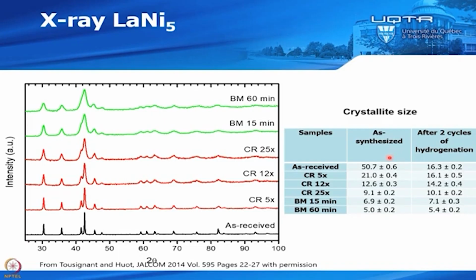So this is as received, it's 50, this is in nanometer, so 50 nanometer, and ball milling 15 minutes, you reduce that by a factor, almost a factor of 10. So it's 6.9, and 60 minutes, you go down to 5 nanometer. While for the cold roll, you see it's 21 nanometer, and then 12, and then 9. So you have a reduction of crystallite size, but not as important as for the ball milling. Okay. And this is after 2 cycles of hydrogenation.